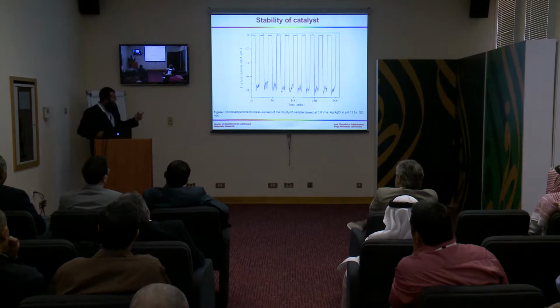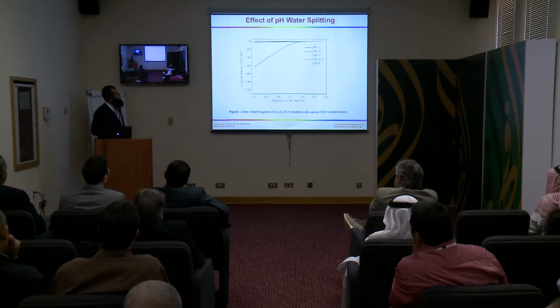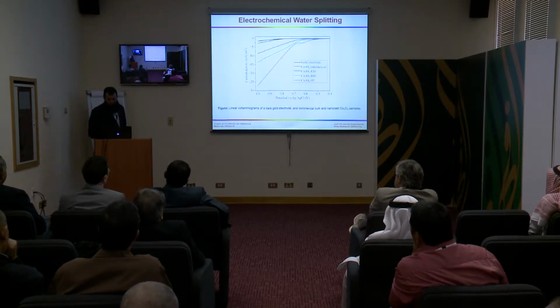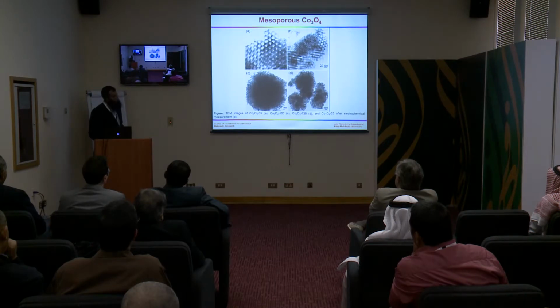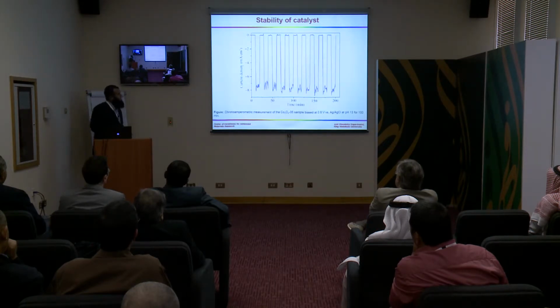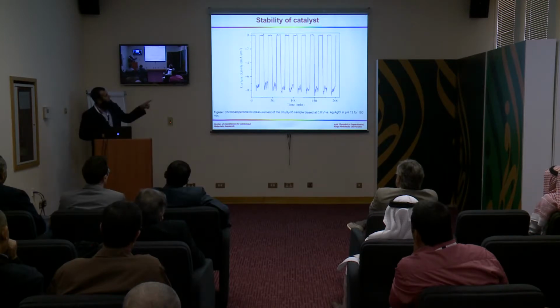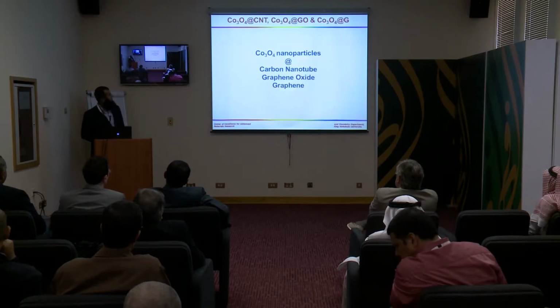But when we applied a high potential of 0.8 volt to our material, for almost 200 minutes it is stable. There is no deactivation in the electrocatalytic property of this material.